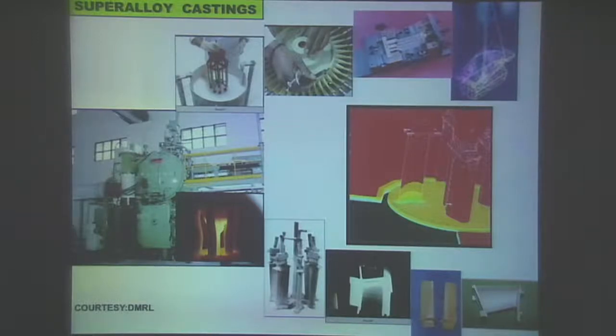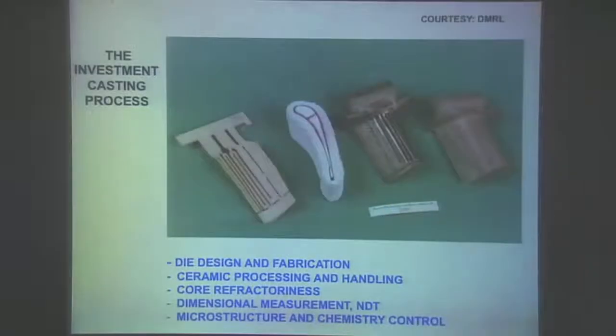You dip the wax, which has the ceramic core, into a ceramic slurry. You fire the ceramic, make it strong. You remove the wax by steam injection. So now you have a hollow with a ceramic core, which resembles the final shape of the blade. And then you cast the material, and you cast it with a controlled heat extraction to give you directional solidification, or if you want, single crystals. So again, a very complex technology for a variety of reasons, because it involves not just metallurgy, it involves die design and fabrication. And why is die design important?